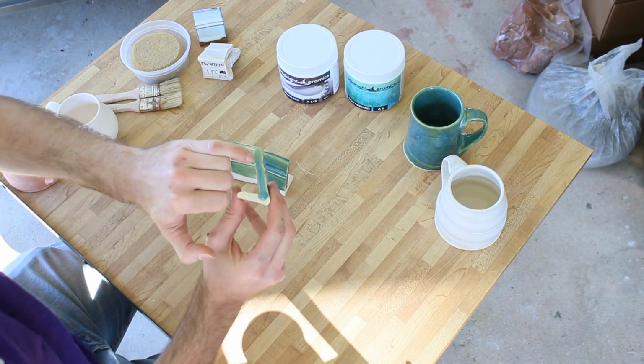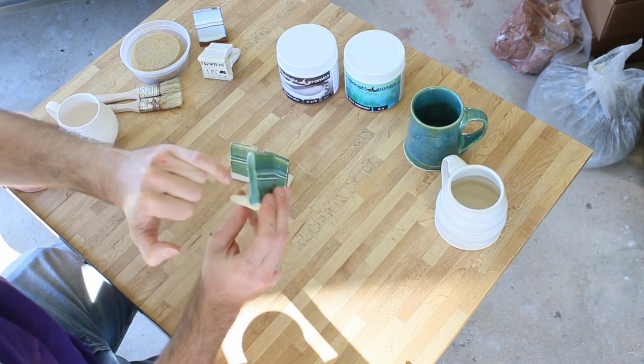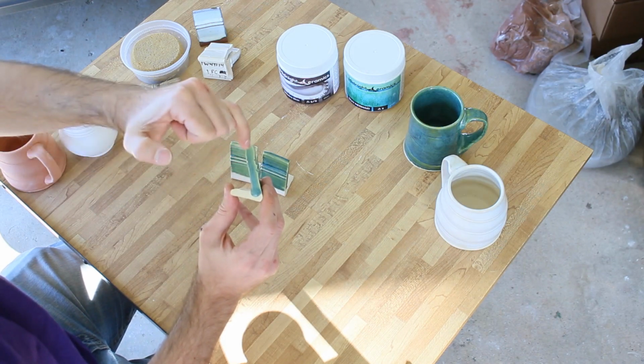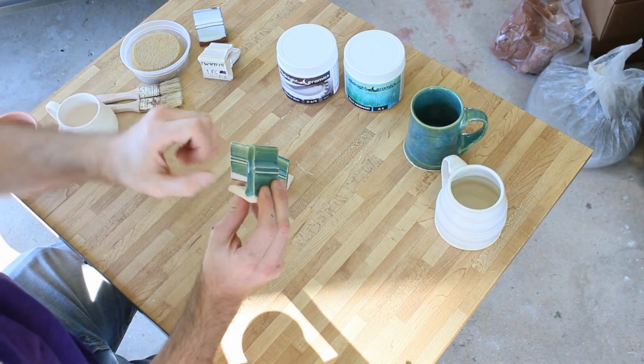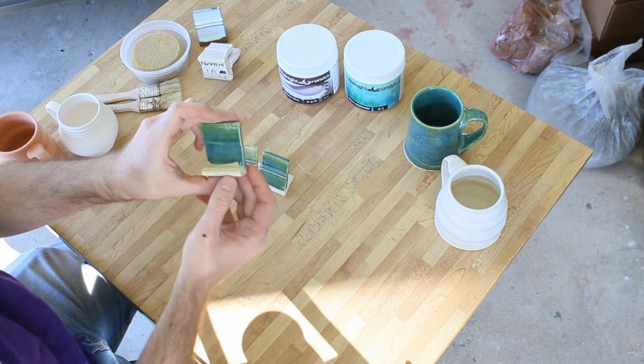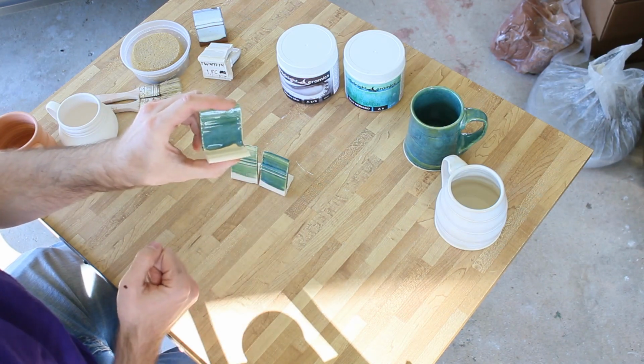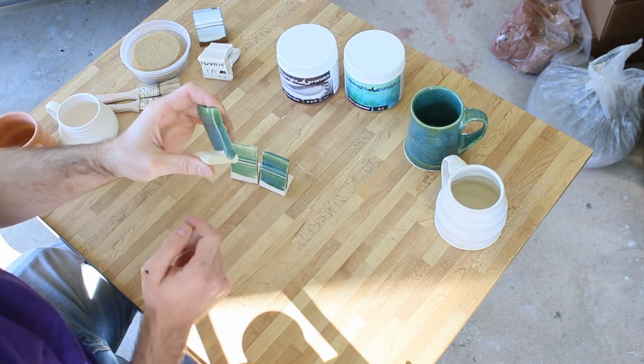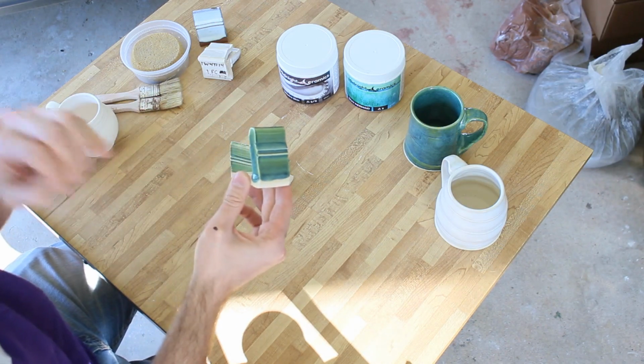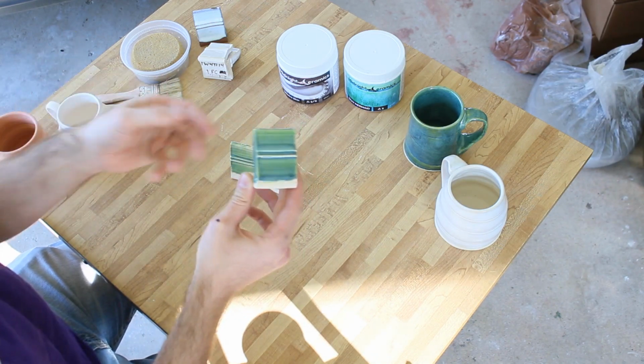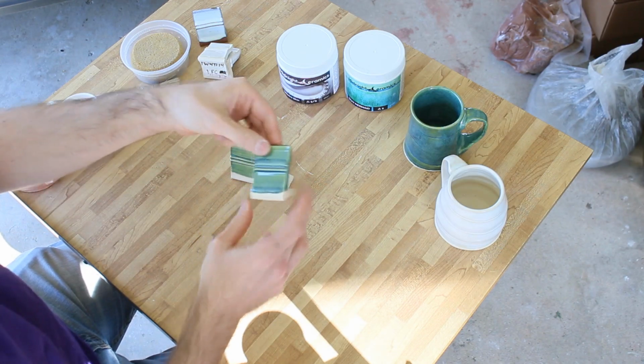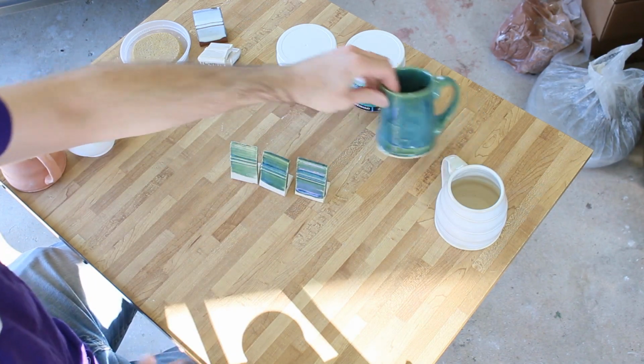run. And if we look at the side of this test tile where there's no texture, the glaze is really permitted to run, and it ran a good half an inch, it looks like, because on the back we can see that the glaze really didn't come all the way down there. So this glaze can run a substantial amount if you get it on thick enough to get the right kind of color.